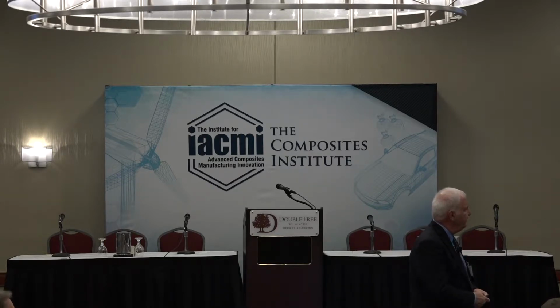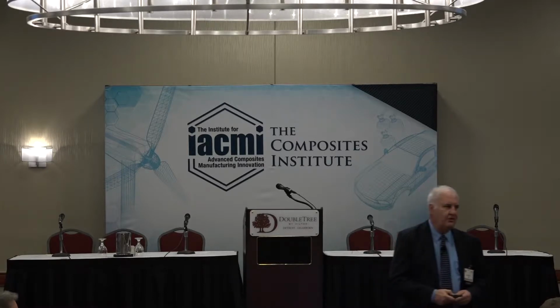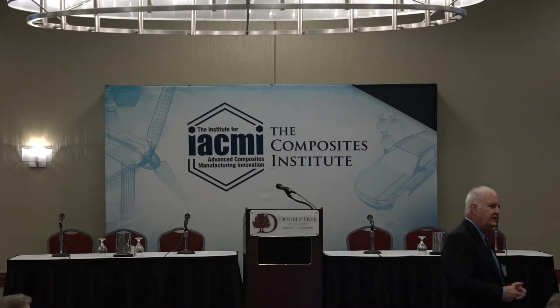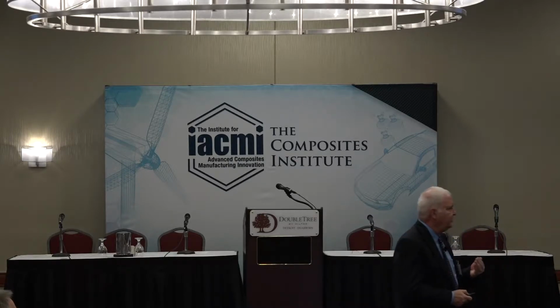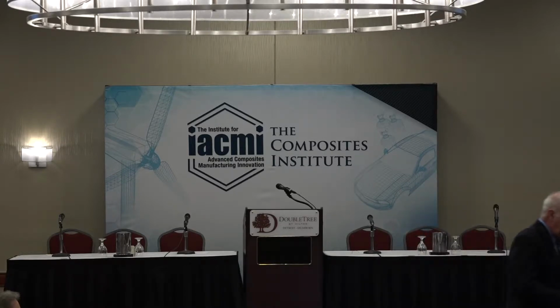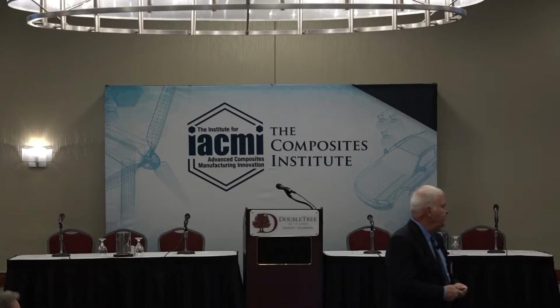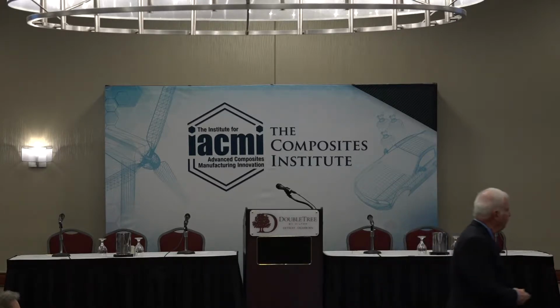And third, we wanted to demonstrate advantages relative to epoxy carbon systems, which are really the incumbent when it comes to many prepregging applications, both automotive and non-automotive. Really, our motivation going into the project, we felt that vinyl ester resins could offer some significant processing and cost advantages relative to epoxies and other prepreg systems in terms of processing and molding times. And also just looking at previous work, we felt that there was room for significant improvement in the resin fiber interface, which in turn influences the mechanical properties of the composite.